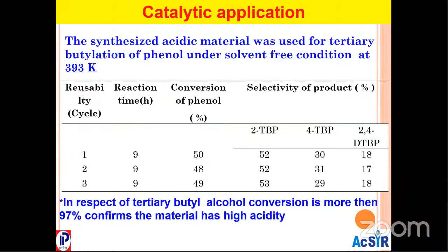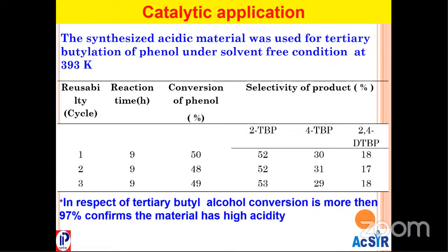Now I am going to talk about the catalytic application. This material was used for an alkylation reaction. As you know, phenols are very important candidates for the preparation of polymers in industry, so I chose this reaction, and the basic research question is that I want to see the effect of porosity, right? How does porosity affect? If I use a non-porous sulfonated carbon material, we have less selectivity for 2,4-ditertiary butyl phenol. But in the case of porous material, we have more selectivity for 2,4-ditertiary butyl phenol.